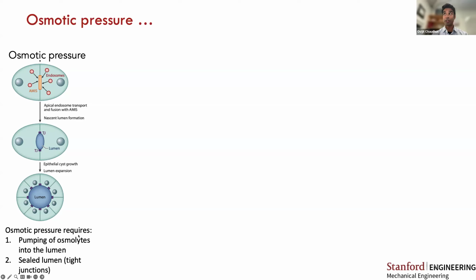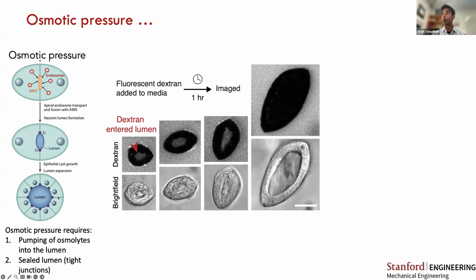Now, what's required for this mechanism to occur is that you need to have sealed lumens, so the junctions between the cells need to be tight. So we first tested whether we were observing tight junctions in our epiblast-like structures. We added fluorescent dextran to the media in our hydrogels and wanted to see whether it entered the lumen readily or was excluded if there were tight junctions.